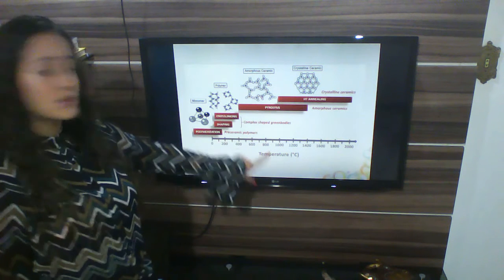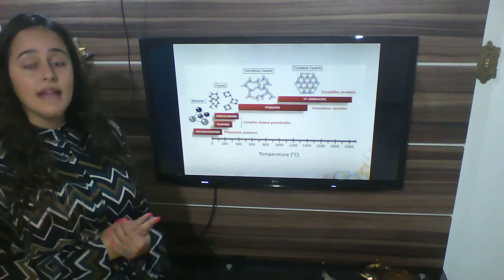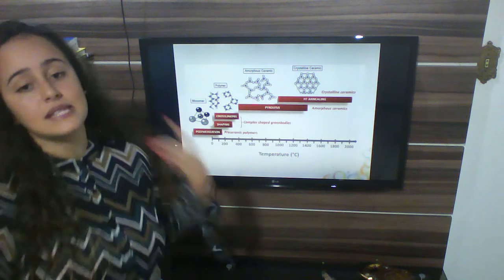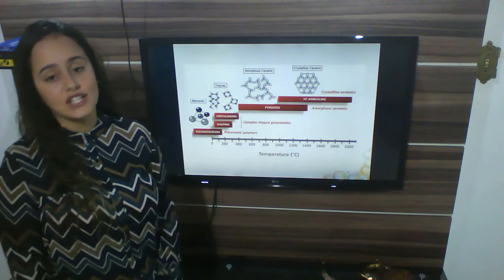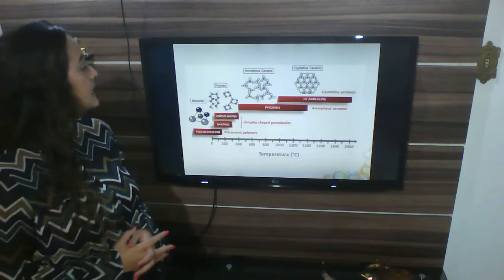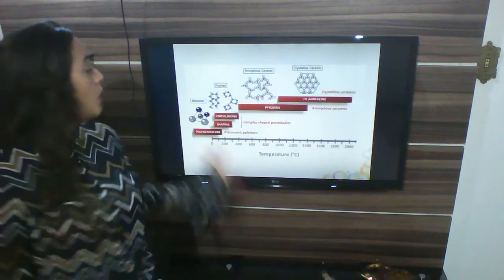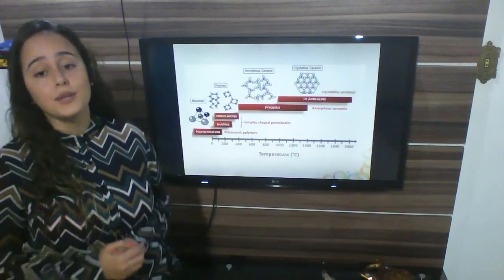Above 400 degrees Celsius, reactions and radical rearrangements lead to the breaking of chemical bonds and the detachment of functional groups from the main polymer chain, macroscopically observed as gas released during the pyrolysis. At 800 to 1000 degrees, the organic to inorganic transition happens, followed by a shrinkage of over 50% in volume, mass loss, and density increase. Now we can see the polymer after the pyrolysis became an amorphous ceramic. All these steps result in a lot of defects, such as pores and cracks, detrimental to the mechanical properties.